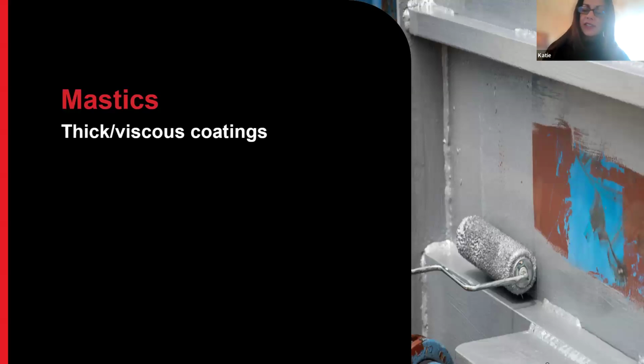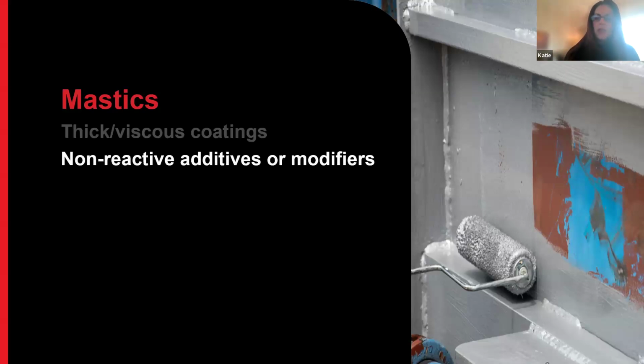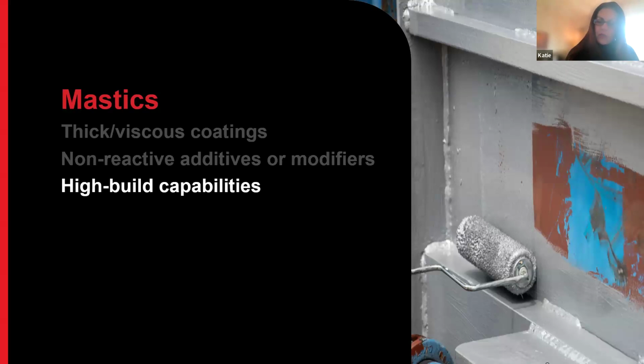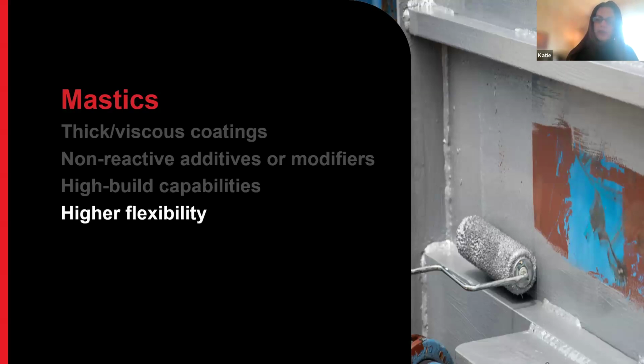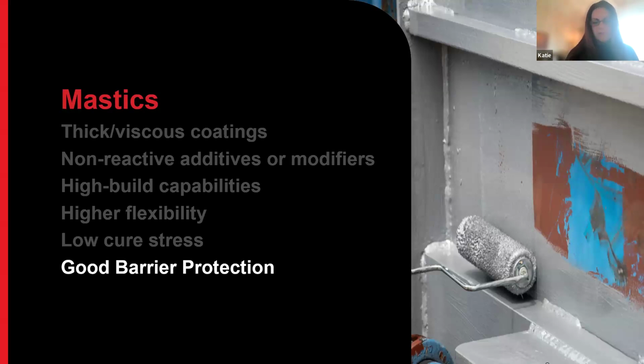These are thick or viscous coatings. They're usually very user-friendly for brush and roller applications. They employ non-reactive additives or modifiers. That means that they don't react or affect the molecular structure or cross-linking, but they do give the coating additional properties like high build capabilities, higher flexibility, and with higher flexibility, you get lower cure stress. And with lower cure stress, you get good barrier protection.